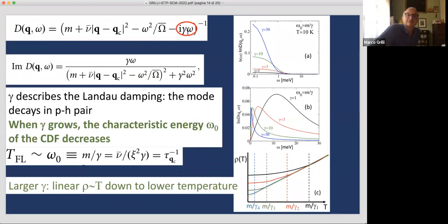Well, the way out can be provided by this Landau dissipation term. This is the term which describes the fact that this charge fluctuation can decay into particle-hole pairs. And now if we look at the characteristic energy of the fluctuation, this is not only given by the parameter m, but it is actually m over gamma. So this is the relevant energy scale. So we can find a situation in which xi stays small, so we stay away from the quantum critical point. We are near the quantum critical point just to have a lot of fluctuations, but we don't go on top of it, so that xi stays finite and possibly rather small.